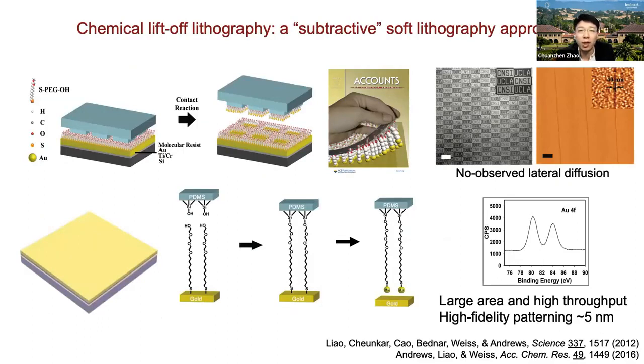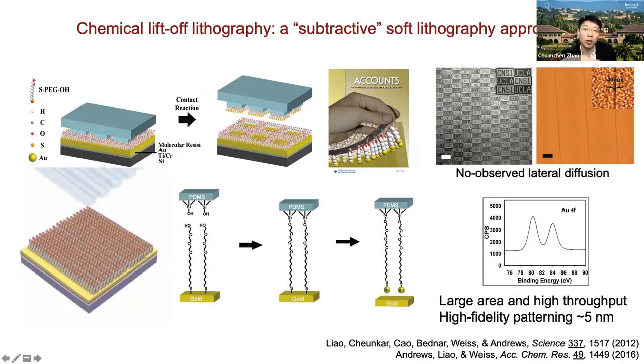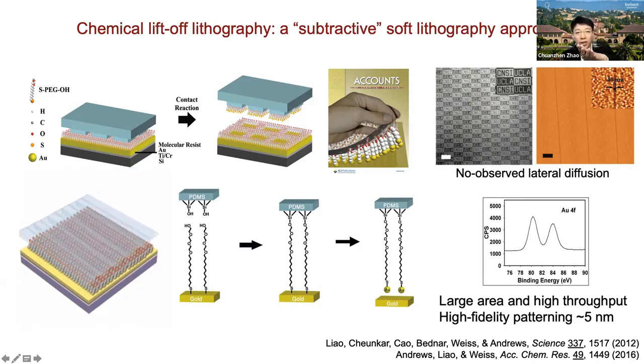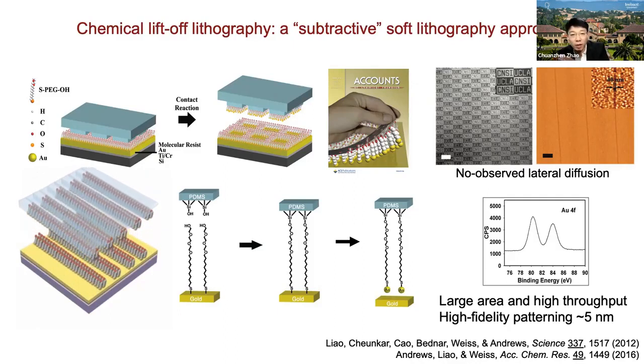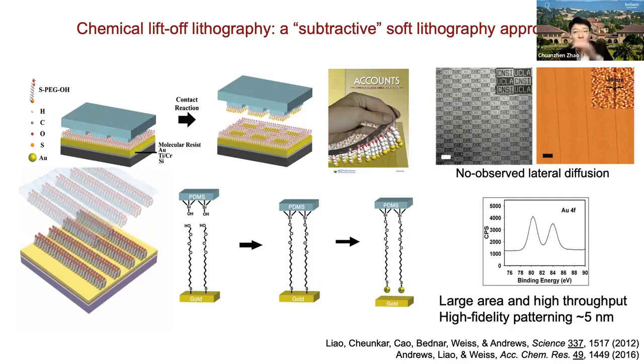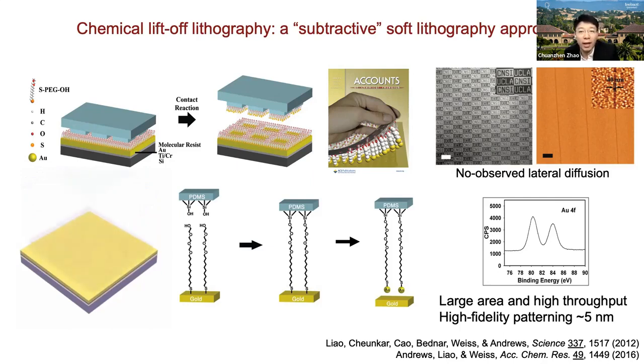To overcome this issue, our group at UCLA developed a subtractive stamping process named chemical lift-off lithography, in short CLL, which has emerged as a promising tool for micro and nanofabrication. In CLL, a self-assembled monolayer of hydroxyl-terminated alkyl will form on the gold surface. Then the oxygen plasma-activated PDMS stamp with silanol group will be brought into conformal contact with the alkyl molecule, and the condensation reaction will then occur between those two hydroxyl groups. Upon lift-off of the stamp, it will selectively remove the hydroxyl-terminated alkyl only in the contact area.